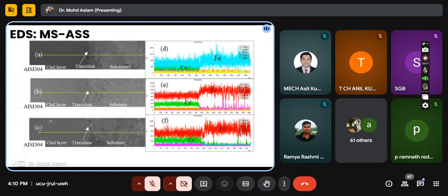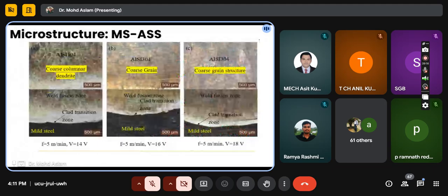So my purpose in showing this one is that I want to identify the clear reason for these things. After that, what are the microstructure problems? Here, at the lower voltage, we have observed that the grain growth size is more, because there is very little dilution time. The grain growth size is more compared to higher voltage, because when melted at a higher temperature, it takes proper time to regain the microstructure in a proper manner. So that's why at a lower voltage we have found higher grain growth, and of course a columnar dendrite structure